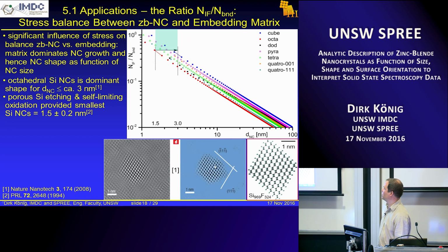And the resemblance is obvious. So they also came up with the fact that the dominant crystal form up to 3 nanometers is this octahedral form with 111 faceting. And that's simply for energy reasons, because the lowest surface energy you have is 111 faceting. Unless you go very far out in indices like 433, but then if you want to hit another bond with a 433 index, you need a crystal which is much bigger. Otherwise you can't define a plane.